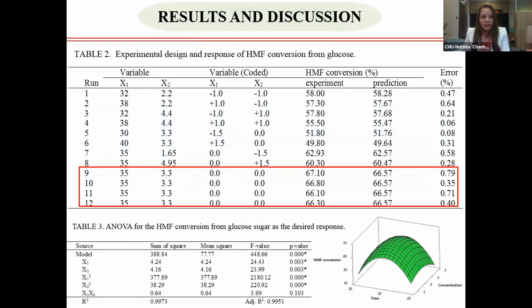The results show that Table 2 is the design of experiment by CCD. The experiment results are from testing 12 conditions for HMF produced from glucose. The HMF yield from glucose ranged from 49.8 to 67.1% depending on the experimental condition. It was found that the acid concentration of 3.3 and 35 minutes of operation time is the optimal condition, with the highest yield of HMF, for experiment runs 9 to 12.